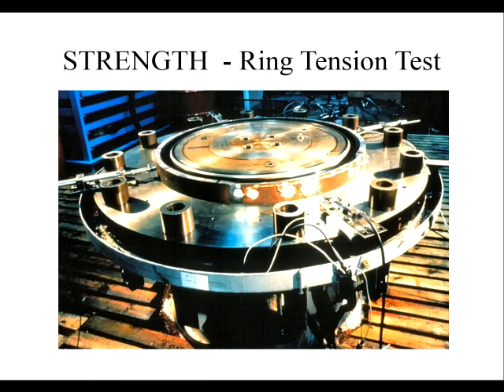So that's a ring tension test system. Here's the pipe, and there are these gauges here that measure the diameter of the pipe to measure the strain, and then there's usually a cam-driven system in the middle here which expands that central part outwards to provide the stress on the system. Clearly that's a much more expensive test than the simple tensile tests, but you can do that.